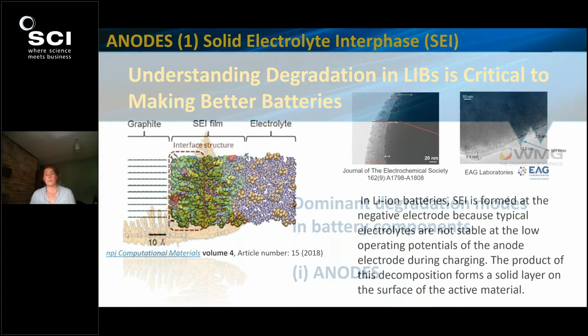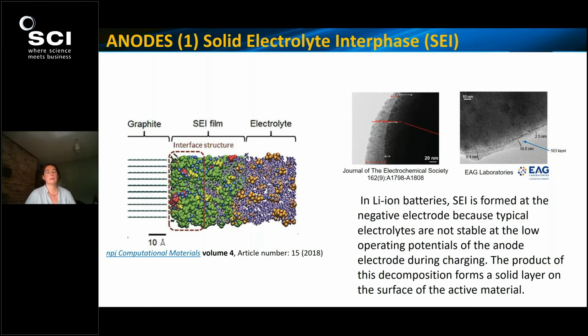When we first charge a battery, we make some significant chemical changes on the surface of the anode. You can see the schematic on the left. We generate, at lower voltages, some partial electrolyte decomposition. Now, the electrolyte is based on a combination of a number of organic carbonate solvents, chosen because they have very good diffusion properties for lithium ions. It's depicted rather simplistically, but the solid electrolyte interface is a very complex structure. It's a passivating film that forms with the decomposition products from the electrolyte breakdown and some of the lithium ions from the electrolyte salt.